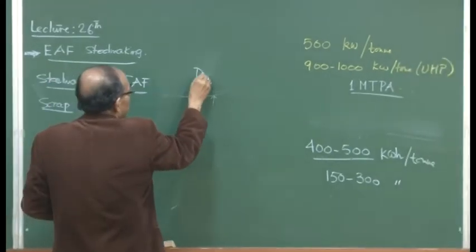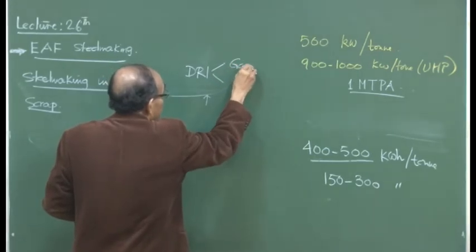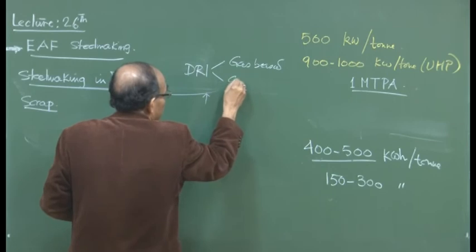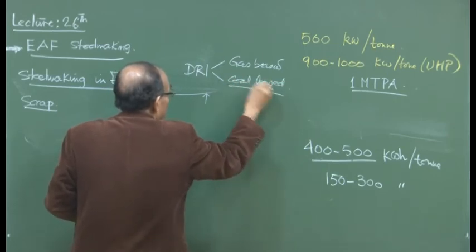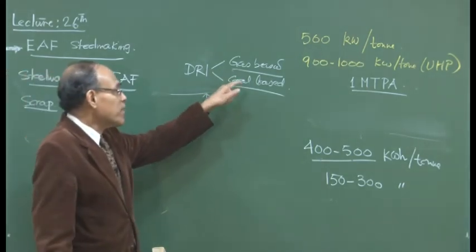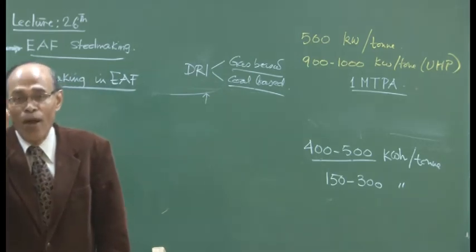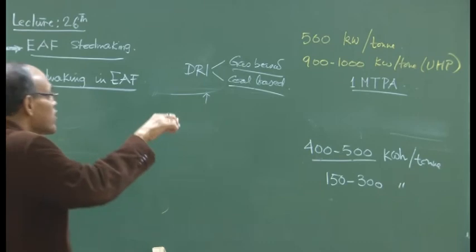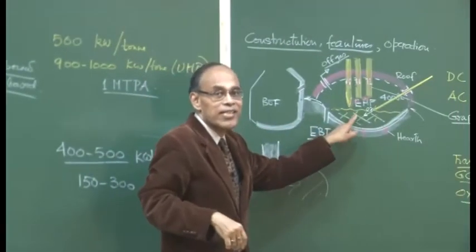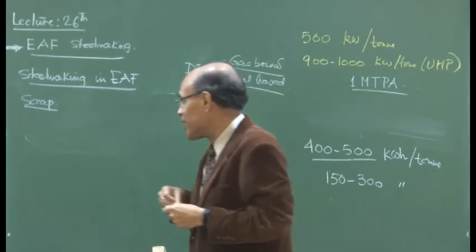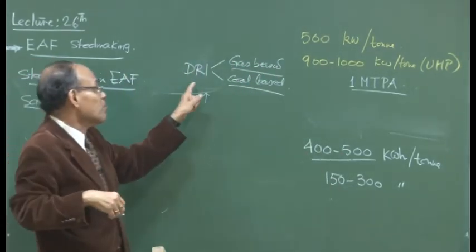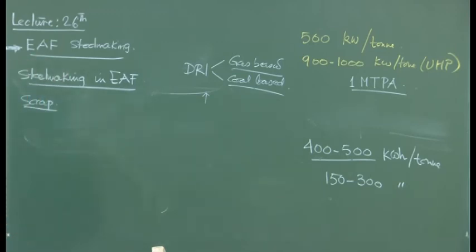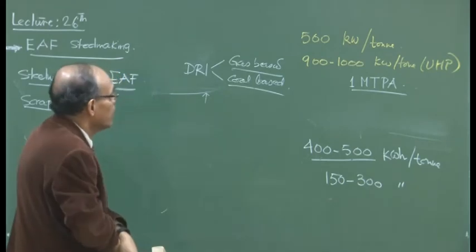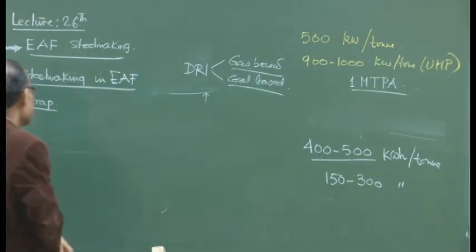The scrap that we use, DRI, as we know that DRI can also be used, and these DRIs could be gas based and coal based. And if you have taken coal based, then what happens is in the DRI quite a bit of impregnation of carbon takes place. So, via the DRI you are charging carbon also into the furnace itself. So, merely charging DRI towards the later part can foam the slag, because there is a good amount of carbon which is present there. Degree of metallization possibly is better in the gas based. So, gas based DRIs are a little bit more pricey than the coal based DRIs, and this is simple because of the fact that you have a higher degree of metallization in gas based DRIs.